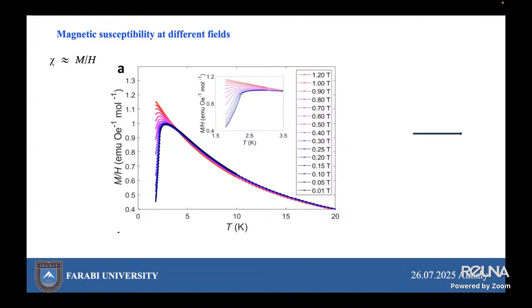ranging from 0.01 up to 1.2 Tesla. As the temperature decreases, you see that the ratio of magnetization to magnetic field increases, first reaching a broad peak around 3 to 5 Kelvin, depending on the field, and then decreases again. The broad peak is indicative of short-range magnetic correlations or magnetic transitions.